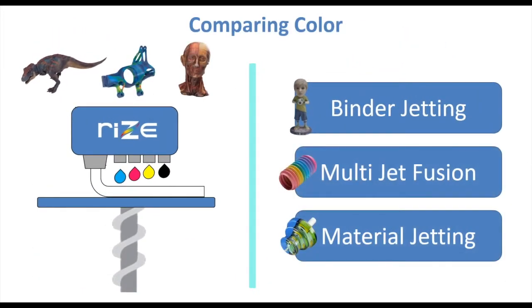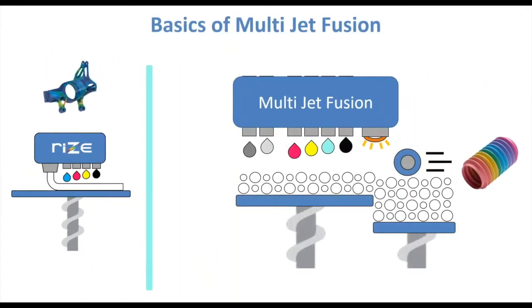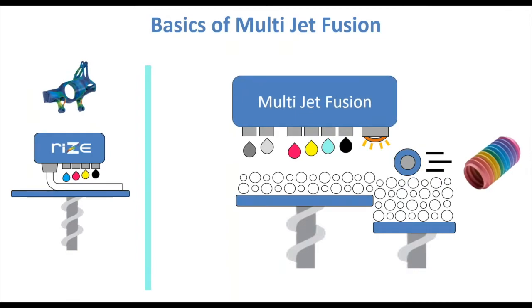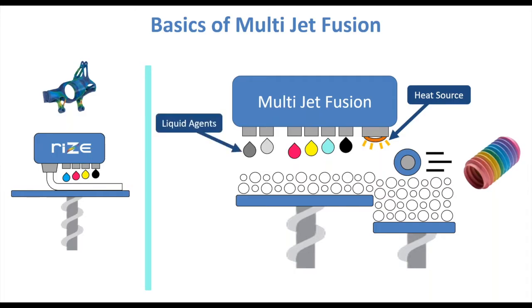So moving on to multi-jet fusion, also known as MJF, which is actually another full color additive technology our founder helped develop. Today it is highly commercialized by HP. And unlike APD and binder jetting here, multi-jet fusion uses special liquid agents that are reactive to selective heating, similar to SLS. And to be specific, the first nozzle pictured here, which dispenses the dark gray agent, makes up the infill, and the light gray agent is dispersed on top of that to act as a primer for the CMYK colors that are dispensed on the part last.